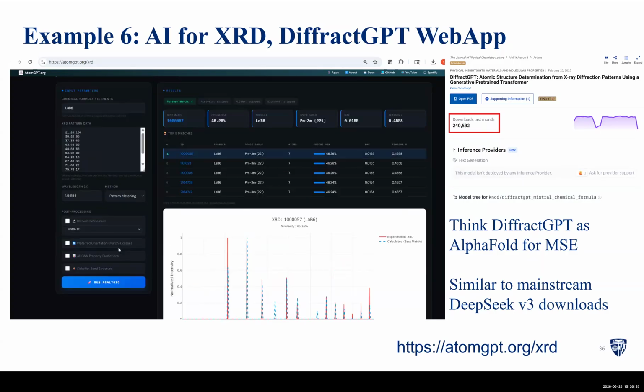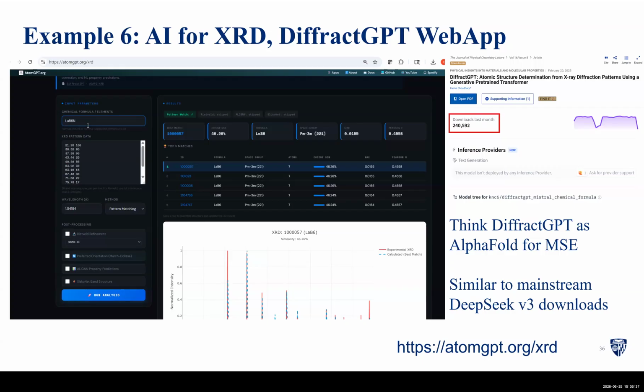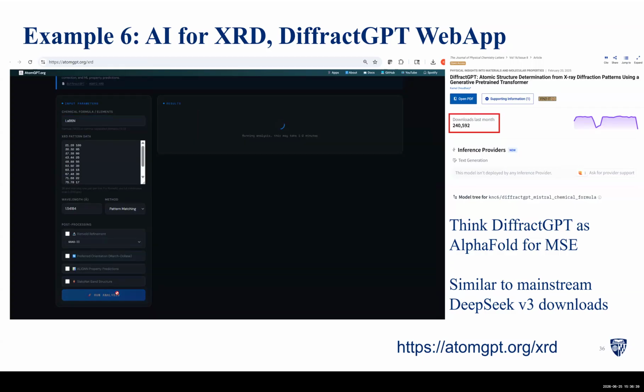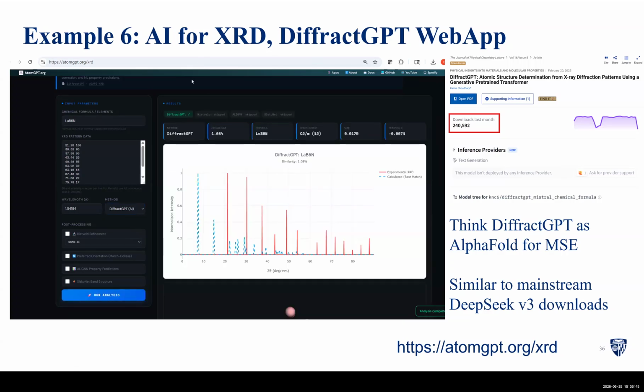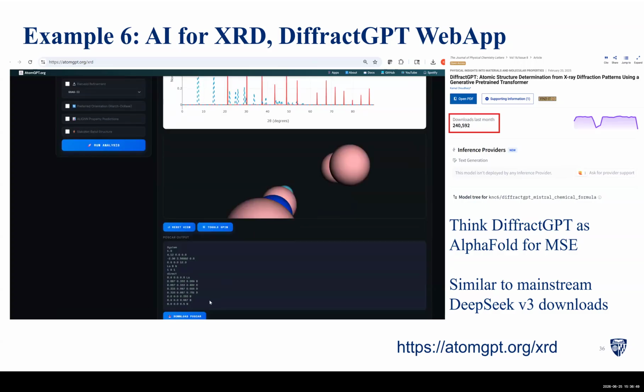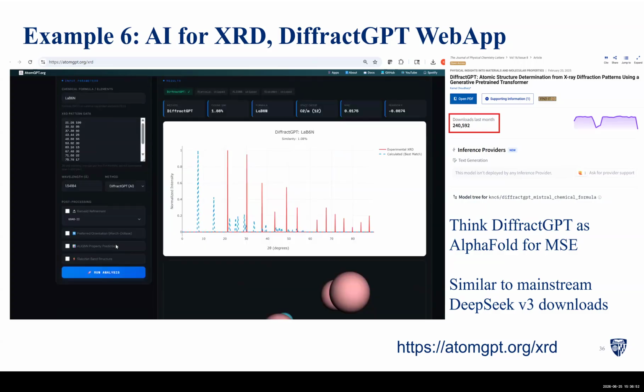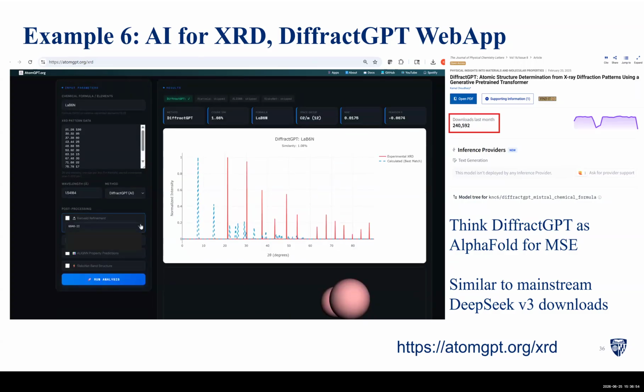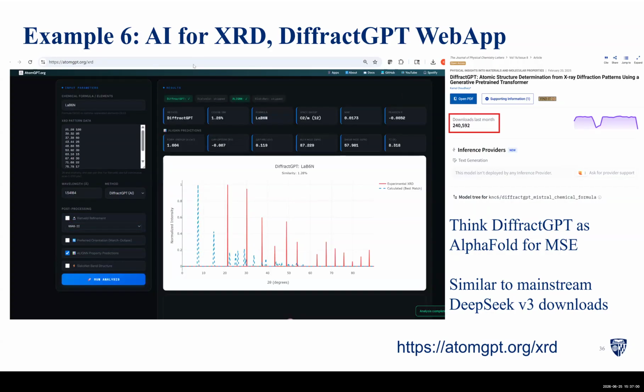So you have lattice parameters, coordinates, and suppose you have LaB6N, which is a material that does not exist. There will be no match. But if you run the DiffractGPT model, as I'm showing you, it will generate a structure. That's the one interesting thing about GPT models: they never say no, they always generate something. So these are a reasonable starting point, at least, and you can also run Rietveld refinement like GSAS, BGMN, and so on, with this model built in, if you have the diffractogram.